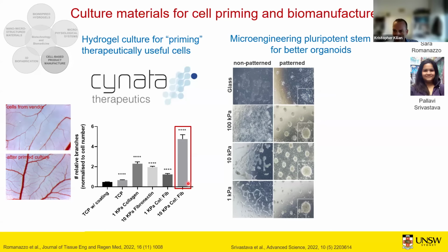Another example is in induced pluripotent stem cells, where we used a soft lithography approach where we micropatterned aggregates of cells on these different gels, now going from about 1 kilopascal, very, very squishy and soft, up to 100 kilopascals, fairly rigid, and showed that by confining cells into these well-defined aggregates, we could coax them to undergo a physiologically relevant transformation. And so they began to undergo development.